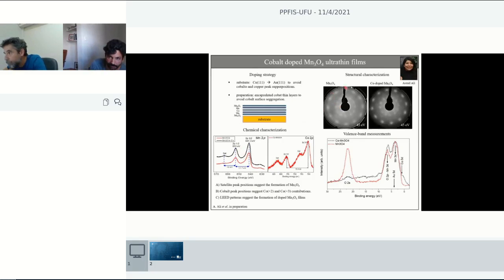We also don't see much change of the doped one in the LEED pattern, so they are pretty much the same. Maybe this is just a matter of a different contrast, but the structural properties appear pretty much the same. But we see in this doped one the peak that corresponds to the cobalt 2p peak. And then this cobalt 2p peak can also be recognized when we look at the spectra, the photoemission spectra